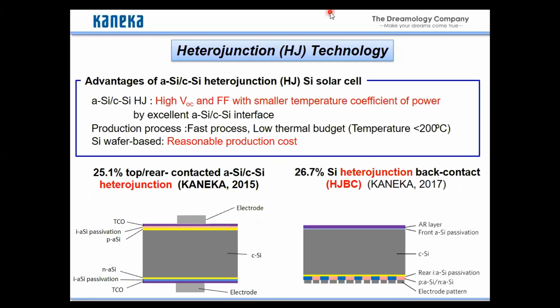So what is the heterojunction cell? In a heterojunction solar cell, amorphous silicon is coated on the surface of crystalline silicon to passivate it, and it leads to high VOC and fill factor, with a smaller temperature coefficient. As mentioned, amorphous silicon is our core technology, and we had long experience, so it was easy to jump into this field. The other aspect is that heterojunction solar cells can realize a fast process with a low thermal budget. The temperature is less than 200 degrees.